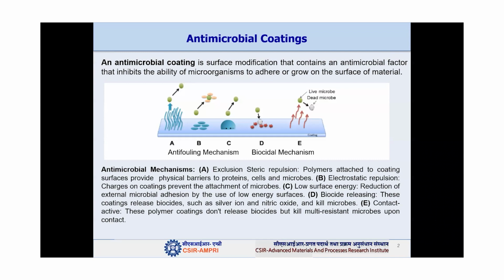So there are different mechanisms by which these coatings kill the microbes or prevent the microbes from attaching to the surface. You can see here that in case A, it can repel the bacteria by exclusion, steric repulsion, or there can be electrostatic repulsion between the surface and the microbes, so it prevents the attachment. Then there are hydrophobic coatings also, which provide low energy surfaces where the microbes are not able to attach, so slowly they leach out from the surface. Or there can be active or biocidal mechanisms also, where when bacteria attach on the surface, some antimicrobial agents release from the surface and kill the bacteria. So it is an active mechanism.